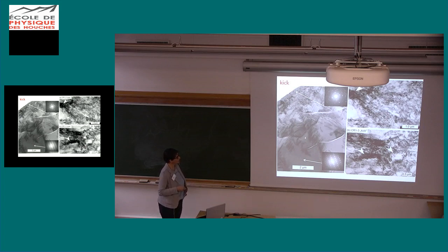These are some areas outside of that area. So we have fractures and these microlites here. We have a high amount of dislocations, but then we also have these tangles, this dislocation forest, and that is of course strain hardening. We increase the dislocation density dramatically, so we have a lot of stored elastic strain energy.